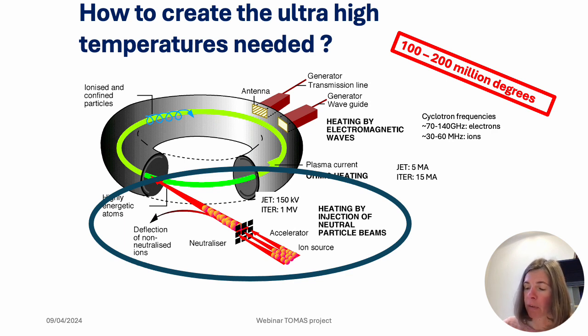Another additional heating mechanism is the injection of a very hot beam of neutral atoms, deuterium or tritium atoms mostly. It can be compared to the steam pipe for steam of your cappuccino. It's a way to heat very efficiently the center of your cappuccino, and this is the same what we will do. We will try to heat the center of the plasma. Of course, depending on the size and the magnetic field, these neutral atoms have to be very energetic, because you want to reach the center, you do not want to heat the edge. To reach the center, we'll have to have neutral atoms that have an energy of the order of 100 kilovolt or even megavolt. And in fact, both additional heating methods, neutral beam heating and wave heating, are very specialized, but I have no time in this webinar to go into more details of these heating mechanisms.